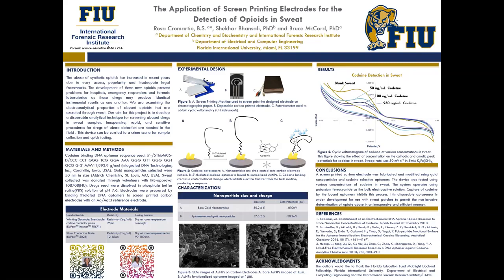So the process material that we use can be seen in figure 1 for the electrode. We use the screen printing machine to create the electrode, and then we put the carbon paste and the silver paste onto the screen printing machine that is placed so that we can make the electrodes on top of the wax printed design. And then we use the potentiostat to measure all the voltammetric measurements that you will see in this presentation.